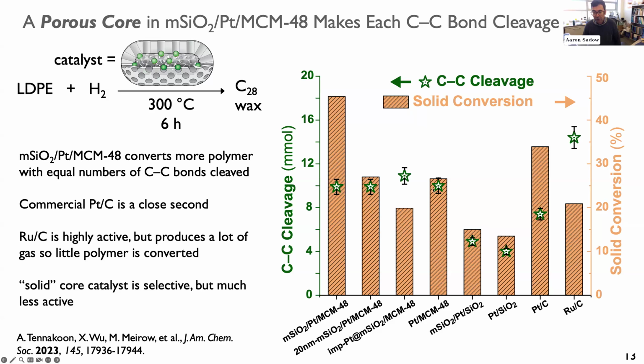It's not the fastest. So these are the speeds for C-C cleavage at a fixed time. And you can see ruthenium on carbon is faster. It breaks C-C bonds at a faster rate per time than this catalyst. And this was the original core shell catalyst here. It's even slower. But you can see how much better this is at converting polymer because we break the chains